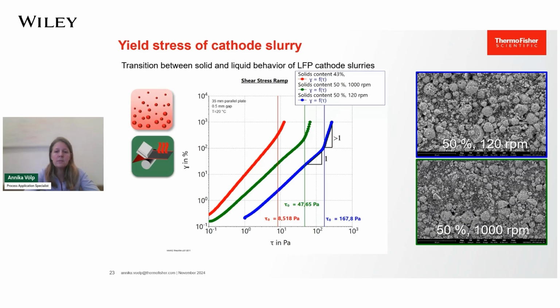The yield stress measurement of the before mentioned LFP cathode slurries are displayed here. The same trend is observed as for the viscosity. The deformation of the slurry with 43% solid content is disproportionately indicated by the slope greater than 1 in the plot throughout the measured shear stress range. This indicates that this sample hardly has a yield stress and is irreversibly deformed at small stresses already.